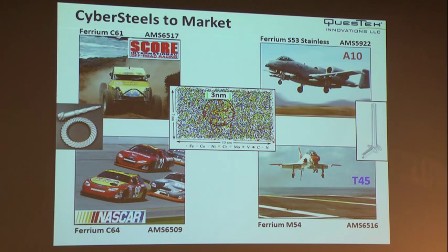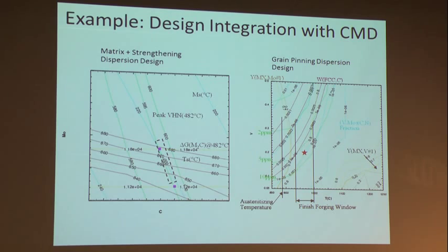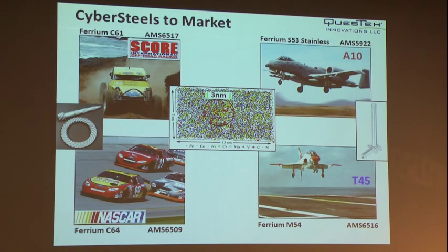So this has yielded the first four commercial steels represented on this chart. In addition to the stainless landing gear steel, we have a high toughness steel for carrier-based applications that's been flight qualified. And we have a pair of very high performance gear steels doing well in off-road racing and on-track racing, and currently being qualified for helicopter applications. All four of these are using that efficient strengthening through the control of the carbides, in which for all of these cases, the carbide size is optimized at this 3 nanometer size as validated by this 3D atom probe reconstruction.